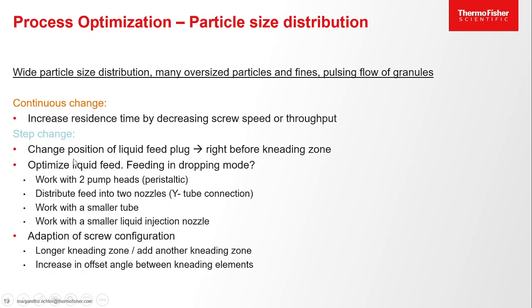Then stepwise, of course, you can think about the liquid feeding, especially the position of the liquid feeding, and also whether the liquid feed is optimized. That means, do I have some dropping mode? So this is not really homogeneously coming out of the pump. In this case, it might make sense to work with two pump heads, or have several nozzles, or work with a smaller tube. So these things can help you to get a more homogeneous flow of the liquid into the granulation process. And then again, you can adapt the screw configuration. A longer kneading section, or an additional kneading section, can help you to increase the residence time, and also increasing the offset angle can help.